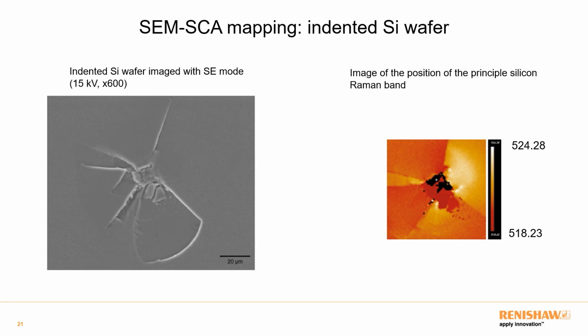And here I just wanted to show you an example of Raman mapping in the SEM. Here we've got an indented silicon wafer, and we've got the SEM image, and this is the corresponding Raman image. Here we're looking at the silicon peak position, which is an indicator of strain and stress. Basically we're able to see correlations between the various different shapes in the Raman image and the SEM image, and we're able to get a little bit more information from our sample.